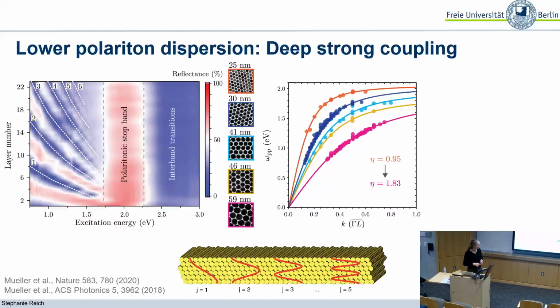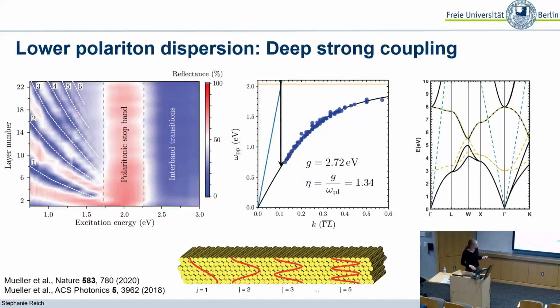That actually leads to my second question. For this interlayer coupling, what you measure is that you always form these FCC structures. And you measure this interlayer coupling around the 1-1-1 direction, right? So that's a close packing direction. If you measure from other orientations, like say 001 or 110, do you think that's also going to affect your interlayer coupling? It will not affect the interlayer coupling, but it will affect the dispersion. Right now we go along this gamma L direction, so that is a typical 1-1-1 growth direction. If we would go along gamma X, for example, that's 001.